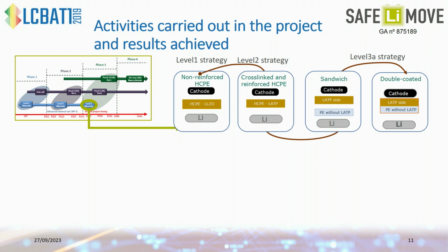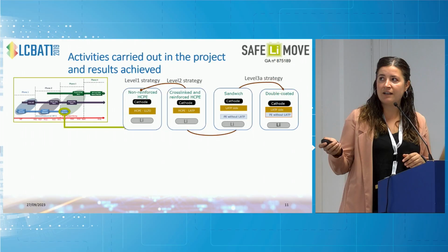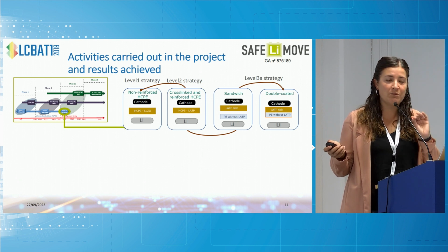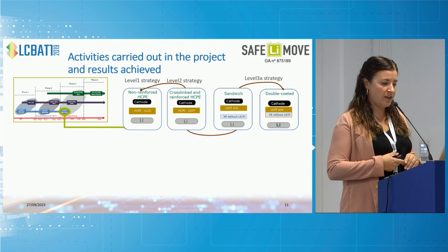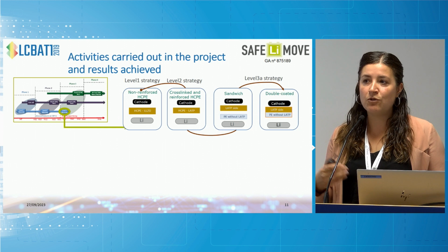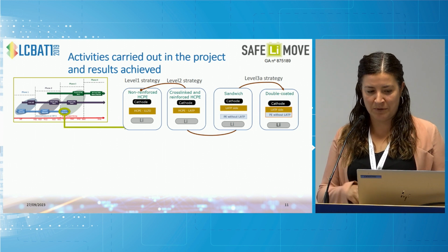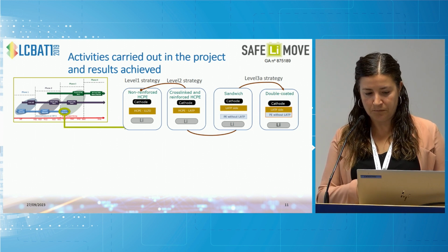And then, in the case of the electrolyte, we realized there were some limitations at the different interfaces. So we designed a bilayer approach where we have a ceramic-rich phase or layer in contact with the cathode, while a soft polymer phase is in contact with the lithium metal. And this was mainly guided by the results that we were obtaining from the previous generation.